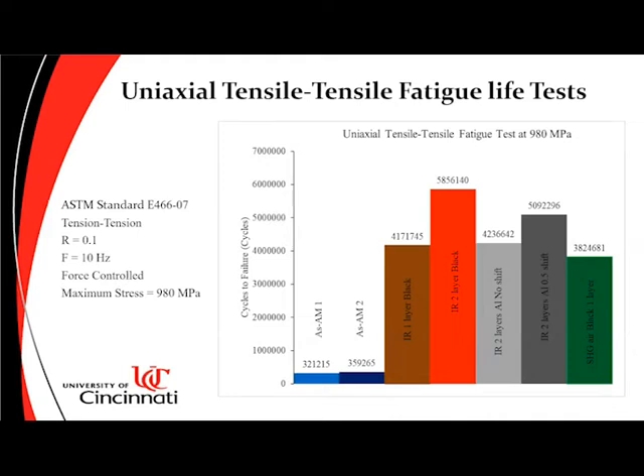So finally, for fatigue testing, we use the uniaxial tension fatigue test. We conducted this at the maximum stress of 980 megapascal, and the result shows the extent of fatigue life improvement due to laser peening. The laser peened samples, as you can see here, show an increase in fatigue life in the order of 10 to 15 times compared to that of the as-built sample, with the infrared with 2 layers of black tape condition having the highest fatigue life.